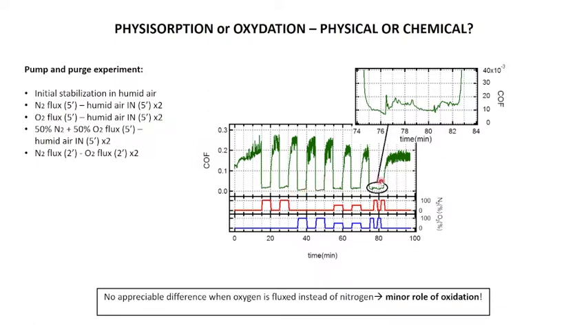And if you look here at this stage, here we fluxed nitrogen and then immediately oxygen. And again, you can clearly compare the coefficient of friction, which stays again very low, in the order of 0.02 or 0.015, something like that. So there is no difference in the coefficient of friction if we flux nitrogen or pure oxygen. And this means that the oxidation plays a very minor role in the failure of the coating, at least at room temperature.